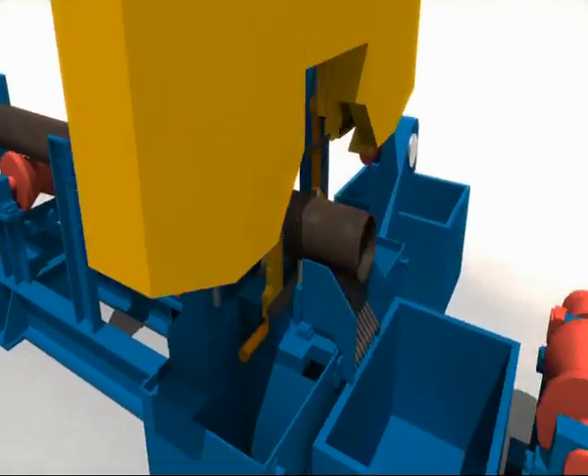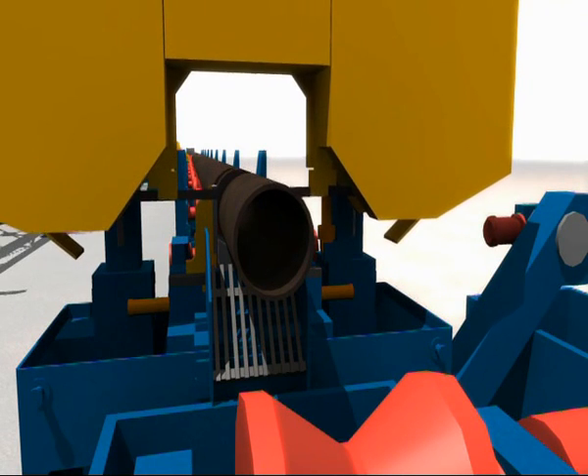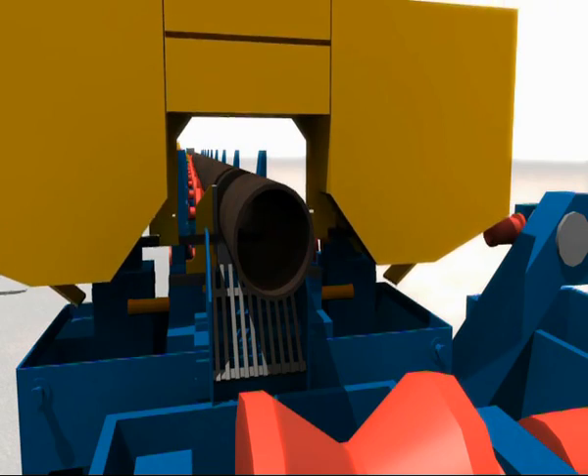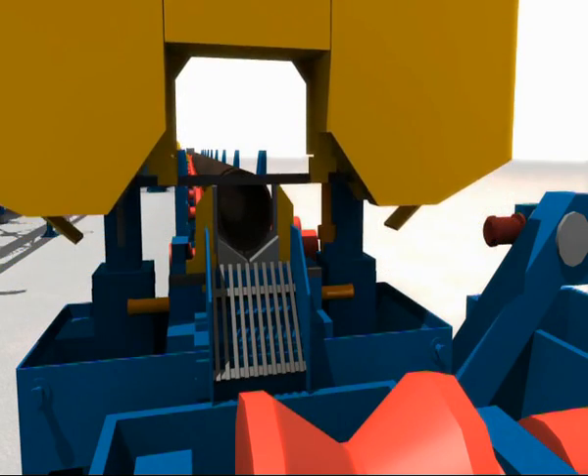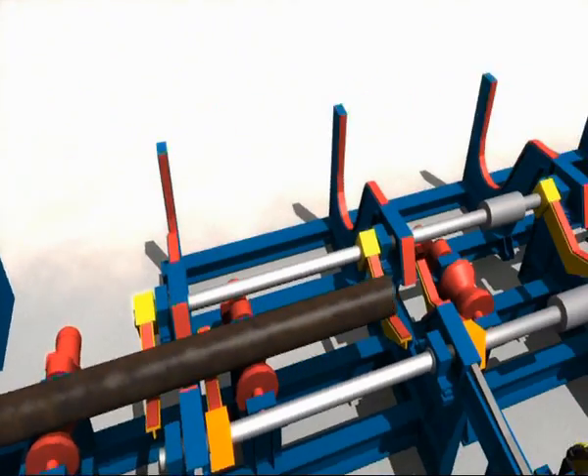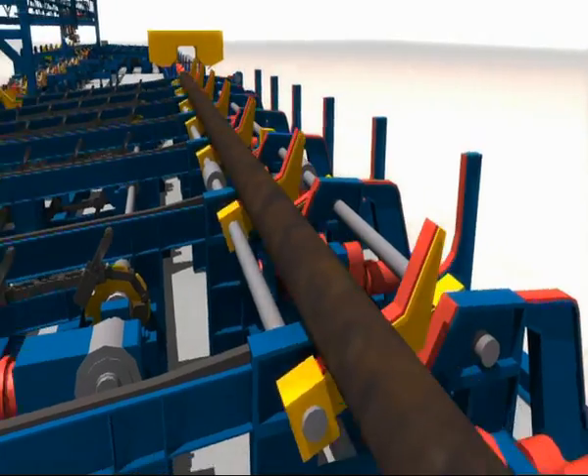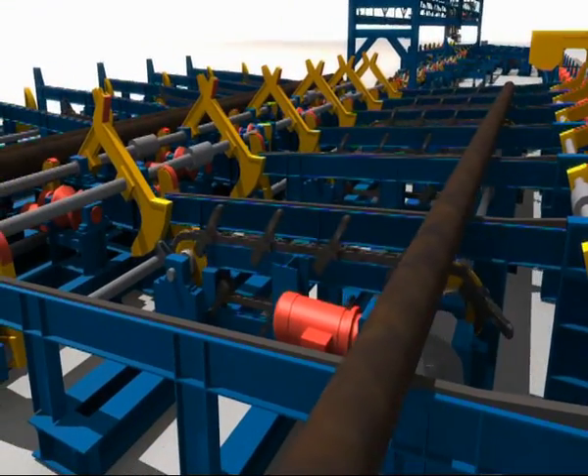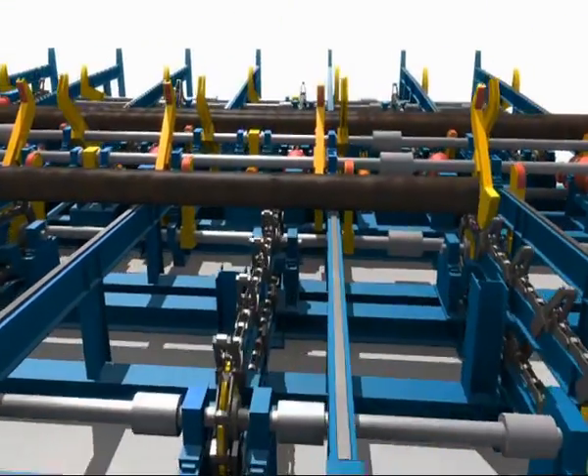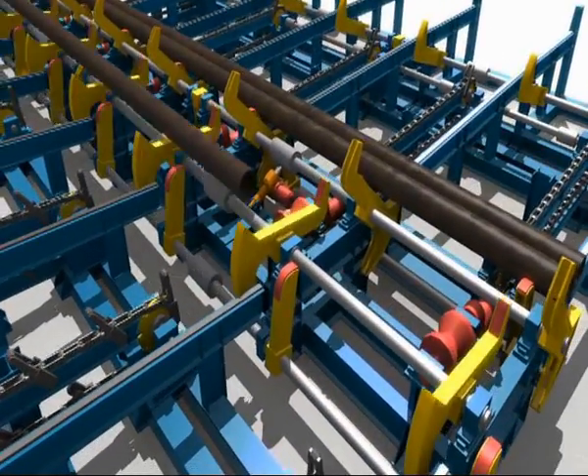This plant also doesn't check the beginning and ends of each pipe, about 100 millimeters, and for this reason, on the threading and beveling line ends, electromagnetic inspection devices have been installed. As previously said, normally the inspection of this machine is carried out after the pipes have already been checked in the quality assurance line and before they are sent to the threading or beveling lines.